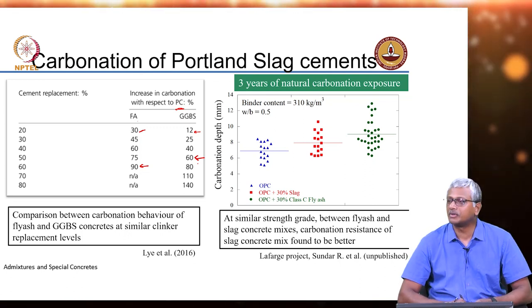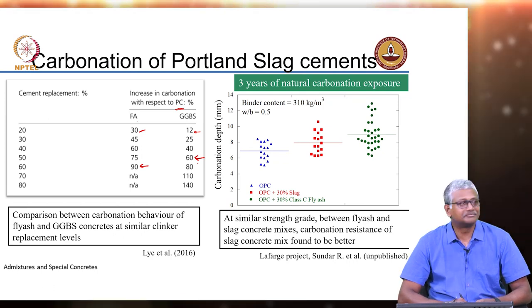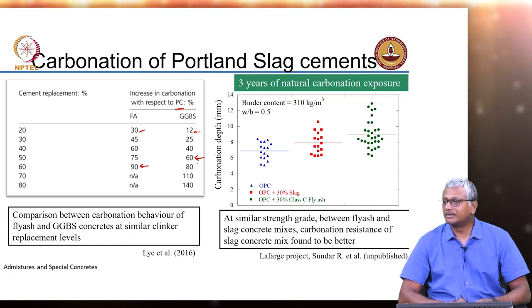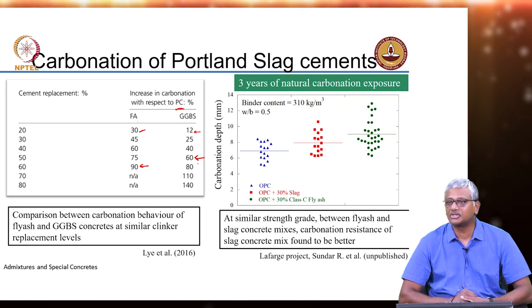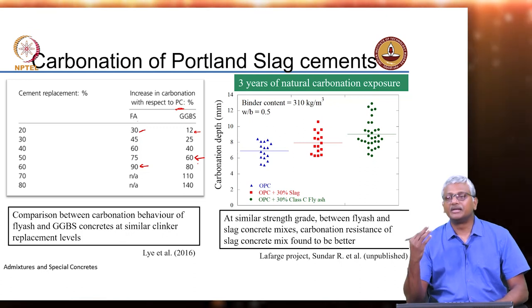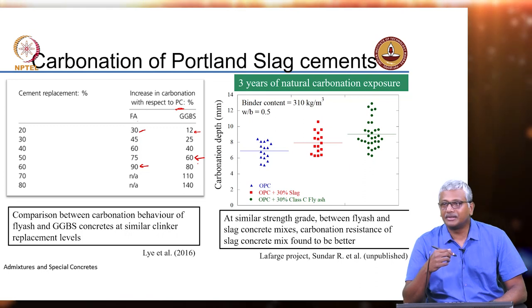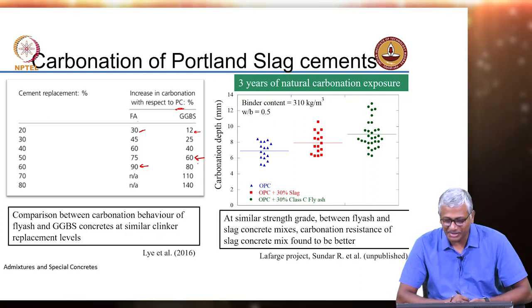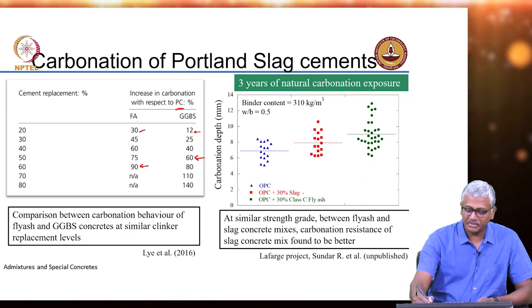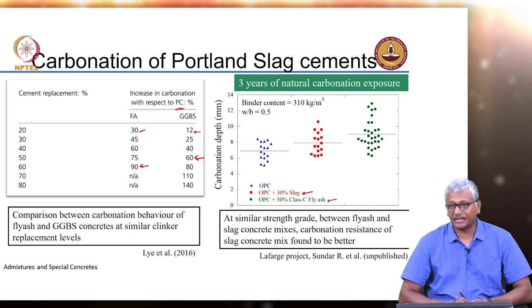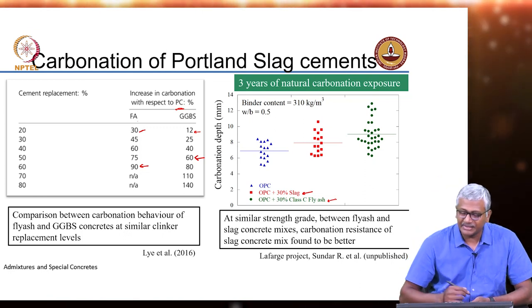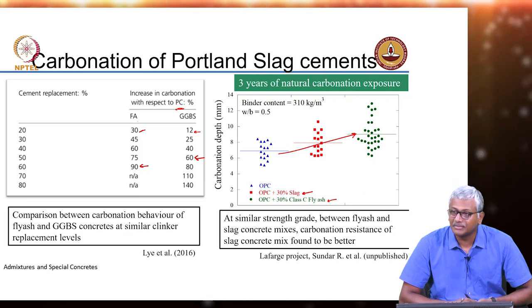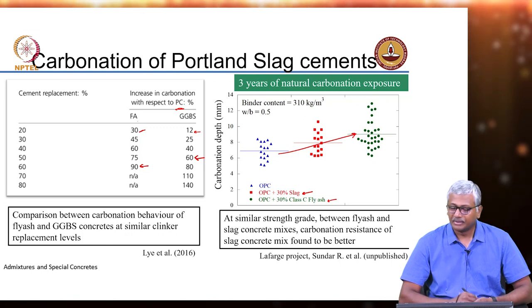That is one reason why you start feeling sleepy in an air conditioned room — if there is not enough air exchange, the CO2 content goes up and increases drowsiness. Anyway, this result presents the comparison of OPC and OPC replaced with 30% slag and with 30% class C fly ash — a high calcium fly ash system. You see that there is some increase as you go from cement to slag to fly ash, but if you check the scatter, it is not a tremendous increase — not such a huge increase that you see.